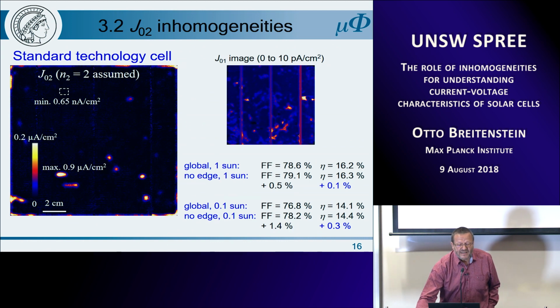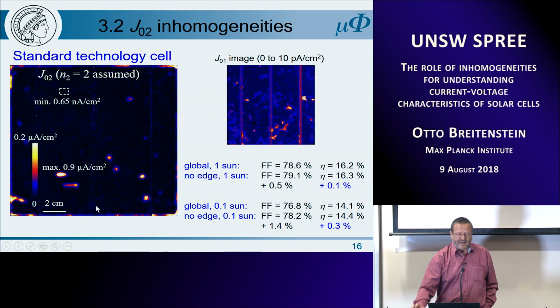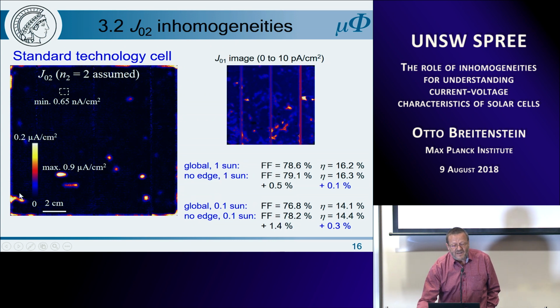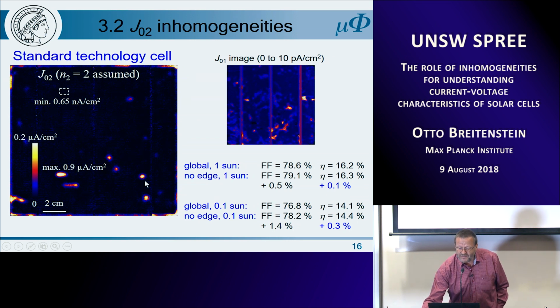So here we see a typical J01 current image, and we see that it is concentrated at the edge. Maybe we should not consider these inner parts, that's a quite old cell, so these are scratches more or less, and these are cracks. But here we have this edge current, and now I have evaluated with a local IV method the whole cell and only the inner part of the cell without the edges. And I found out that at 1 sun illumination intensity, the influence of the edge is very weak, so the fill factor would only improve without the edges by 0.5%, and the efficiency by 0.1%.